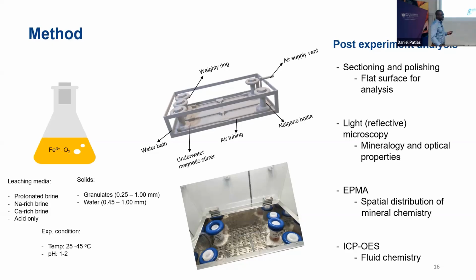We're using granulates, which are coarser rather than fine materials, because we want low energy systems — 0.25 to 1 mm. And then we're using something called wafers, which are rectangular slabs that we cut, which I'll show you soon. The idea was to have a surface which could tell us where the passivates are forming and how it's influencing the system. Post-experimentally we do all these analyses.